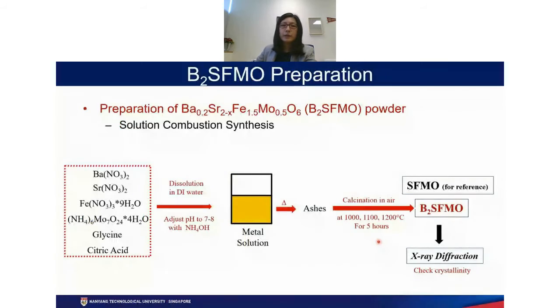So coming to the experimental, this is the preparation of our electrode material. We make our powder with solution combustion synthesis. We mix all the precursors together in DI water, adjust the pH value, and get the metal solution, and then heat to generate the ashes. Then we calcined it at 1000, 1100, 1200 degrees C for 5 hours. And then finally we obtain this BSFMO powder. We also make the SFMO powder for reference, just to compare whether it gets the right phase.